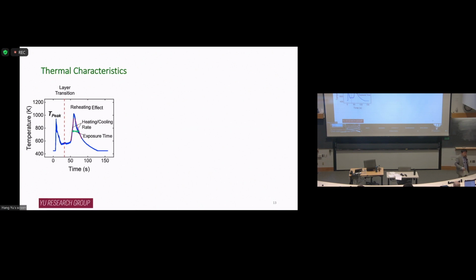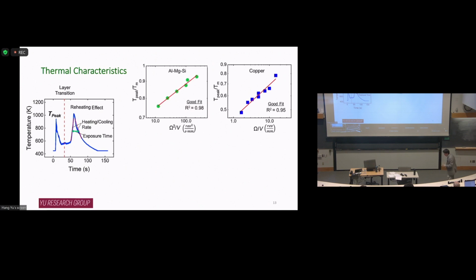So what's important here is we can extract some important thermal characteristics from this plot. One important characteristic is the highest temperature during the process, called peak temperature. Okay? Another thing is the exposure time, like how long the material is under the elevated temperature. Of course, the heating rate and the cooling rate are also important for us. Okay? So we did some kind of parametric study, right?